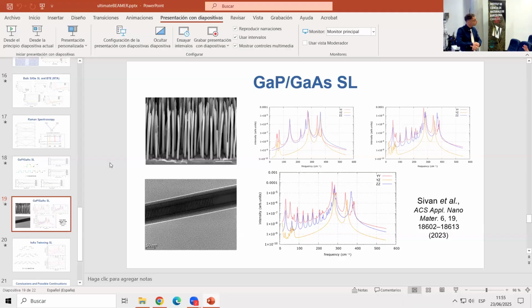So my question was, okay, now I do an experiment, I measure the spectra, and they will be perfectly superimposable to the spectra you computed here, or not? Not perfectly, for several reasons. For example, we can perform the experiments on superlattice nanowires, whereas we can only compute the spectra of the bulk superlattice. We cannot simulate systems as large as the ones we have in the experiments.